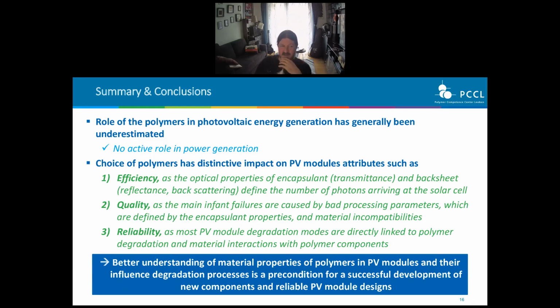Especially, polymers have a big impact on quality, because most infant failures that we observed in the past were caused by bad processing parameters, which resulted mostly in delamination, for example. And then the polymers define the reliability, because most PV module degradation modes are directly linked to polymer degradation and material interactions with polymer components.